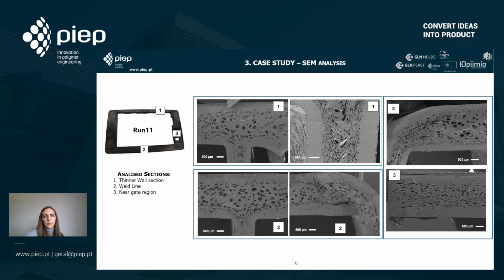We then analyzed the microcellular structure of run number 11 and did the analysis in three different sections. Number one, which is a region that is neither too far from the gate, nor near the weld lines. Number two, which is near the weld lines, and number three, which is near the gate. So we expected to have different cell density throughout the part and different cell sizes, specifically because we have different regions being analyzed. However, we can see some degree of that.